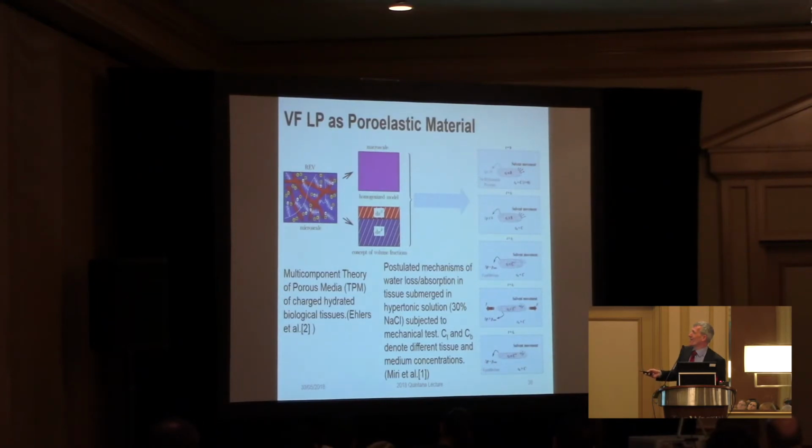In terms of physical properties, all of the soft tissues contain a lot of water. And one experiment that we did in my lab with my former students and Canal, basically you pull on soft tissue in a saline solution and it changes mass. So you pulled on it and waited and then let it relax, waited again. And he did that repeatedly and the mass change was measurable. And it was significant statistically. So I kept sending him back to the lab and saying, you got a mistake and so on. But in fact, this is explainable.